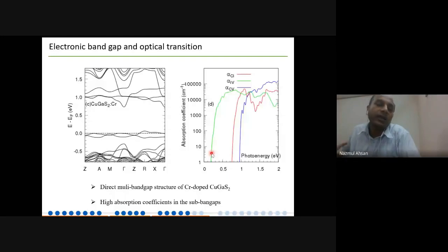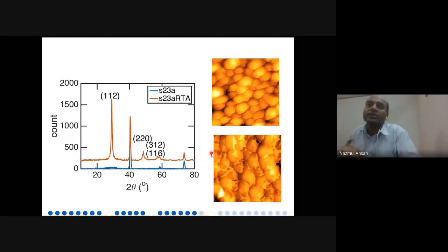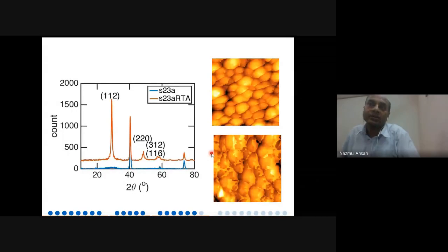Then we started characterizing the materials, and XRD characterization tells, look, we can make a smaller grain. These are made, by the way, by sputtering, not molecular beam epitaxy. This is just as made by sputtering. But if you sulfur anneal them, then you see that the smaller grain is becoming bigger and bigger. And the bigger grain means that the photoelectron lifetime will be very good, and you can have high solar cell efficiency.